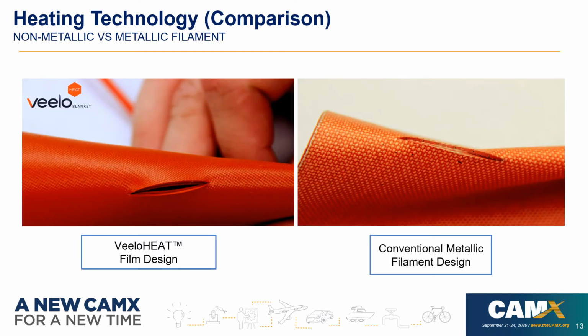So what's really different about this electrothermal film that's carbon-based? Well, comparing this to conventional metallic filament design, we have some slits here that show in the case that the blanket is damaged. In the case of the VeeloHEAT material, if you zoom in close, you can see the continuous carbon film there. And then looking at the conventional metallic filament, you can see the cross-section here of the serpentine filament design.